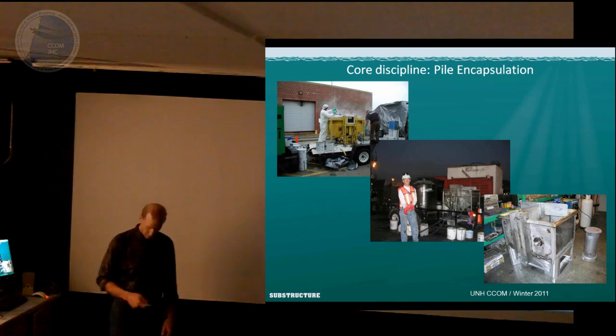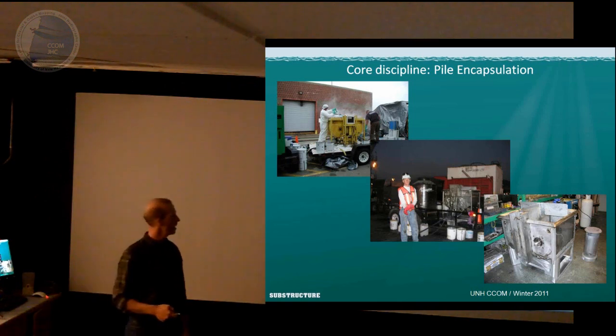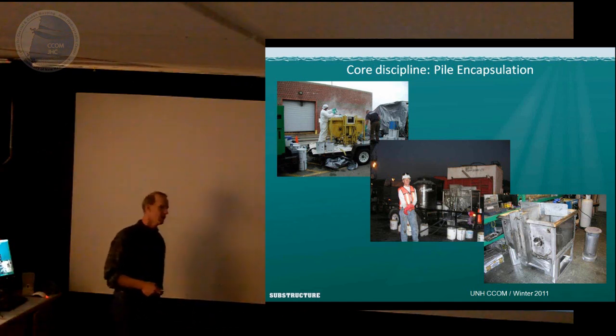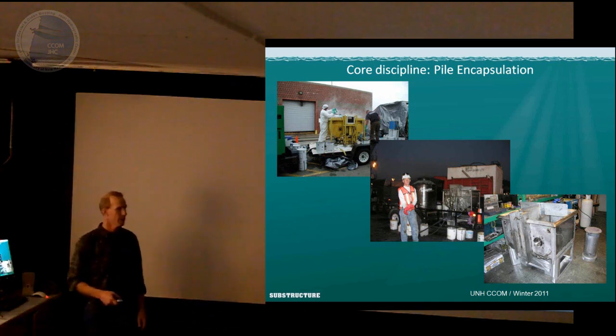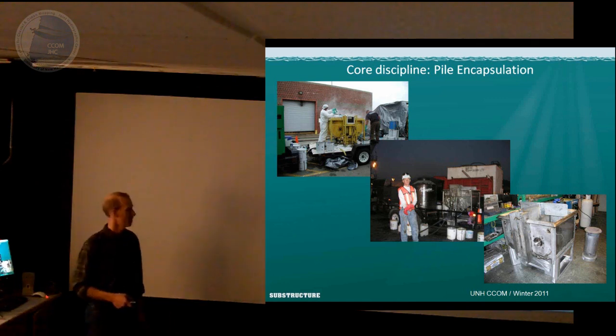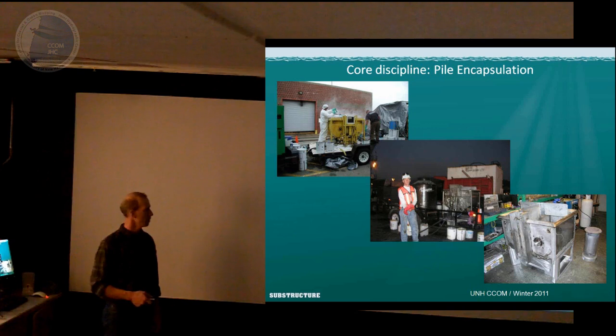It's an incredibly difficult process pumping an aggregate modified epoxy mixture. So it's a plural component pump. There's a hopper for an A, hopper for a B, mix aggregate, which the worker's doing right there into it. So you're pumping gritty honey down a line at 1,500 psi, and it's incredibly difficult to do that and maintain a perfect 1-to-1 ratio. And we've developed the pump to do that, and that's really what we patented.